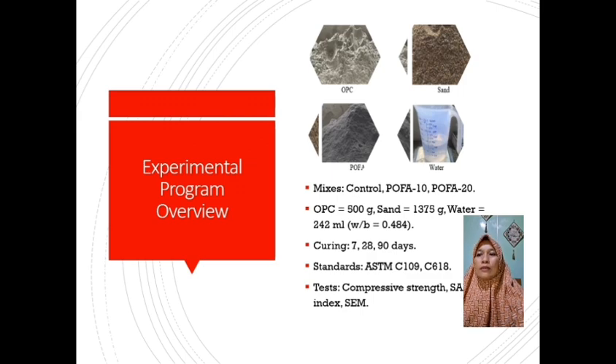The tests followed ASTM C109 for compressive strength and ASTM C618 for strength activity index. Pozzolanic contribution was determined from the ratio of pozzolanic strength to total mix strength.